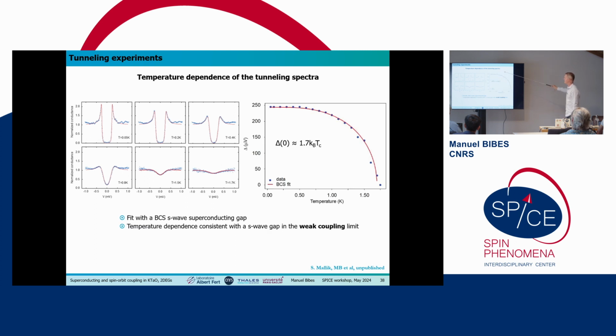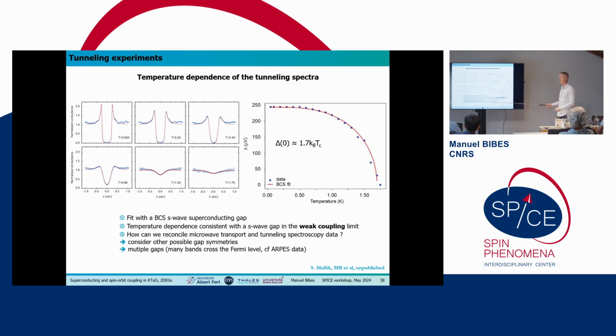That's the gap as a function of temperature, and this is in contradiction somehow with the previous result from the superfluid stiffness, because here it seems to be consistent with the weak coupling limit. So it's just work in progress. We want to find ways to reconcile the microwave measurements and the tunnel data.